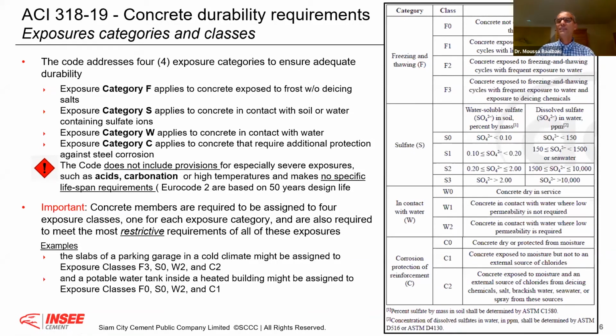The second difference is that if you take ACI, if I have to design, for example, a slab, I need to take the worst condition all the time. I should consider what applies for frost, for sulfate, for contact with water, and for corrosion. For example, this will be F1, S1, W1, and C2. After that, I see what is the worst condition. I design my concrete according to, in this case, C2. That is how they design. Therefore, the engineer needs to consider all of them and take the worst case scenario.